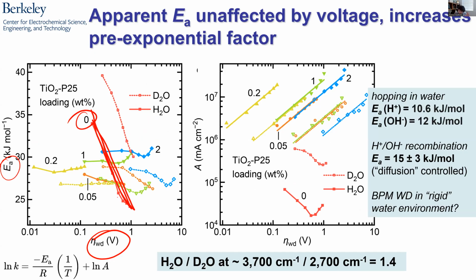So that idea of the local electric field stabilizing the transition state dipole is maybe right when you don't have a catalyst. But as soon as you have these catalytic materials, there is no dependence. These are the different loadings. They all have different performances, but there's no strong dependence of the activation energy on driving force.